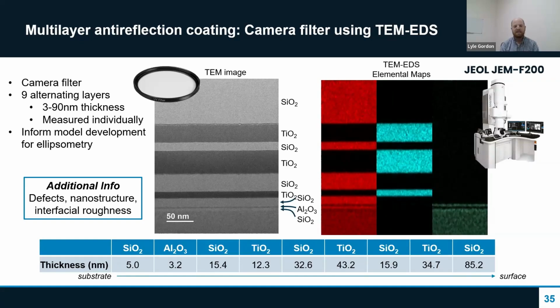So using this data, we can build the model for ellipsometry, but also in this case, we can just directly read off the thicknesses from these layers by measuring through a line profile on the image. And then we also get insight into, for example, the interfacial roughness and any defects and the nanostructure of the coatings. In this case, everything is amorphous without a lot of crystalline structure, so we don't see much, but in many cases, you can get a lot of insight into the different materials in the coating.